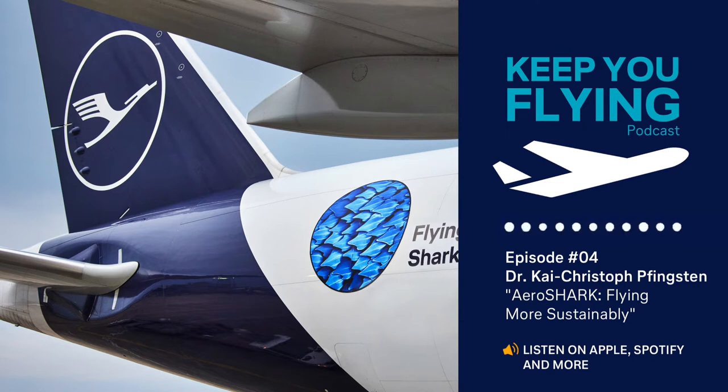Until now. But before we look at the most recent developments, let's go a few years back again. Already in 2011, we entered a cooperation with Fraunhofer IFAM and Airbus to investigate the application of riblets on aircraft. After the so far rather unconvincing experience with applying adhesive riblet films in the aviation community, we tried a completely different approach. Instead of adhering sharkskin films onto the painted aircraft skin, we went with a new technology. The aim back then was to literally emboss the riblet structure into an additional layer of coating. The trick here is that the coating is cured during the embossing process, thus keeping its microstructured surface. The focus of the project, multifunctional coating, was to test the longevity and durability of the microstructures in regular aircraft operations. Therefore, riblets were applied on small spots in the fuselage and the upper surface of the wing to monitor the degradation.